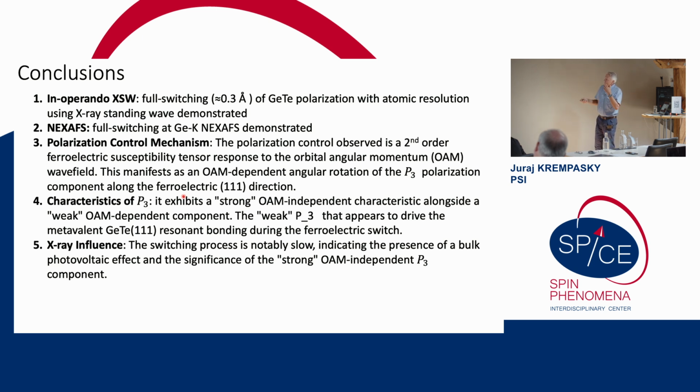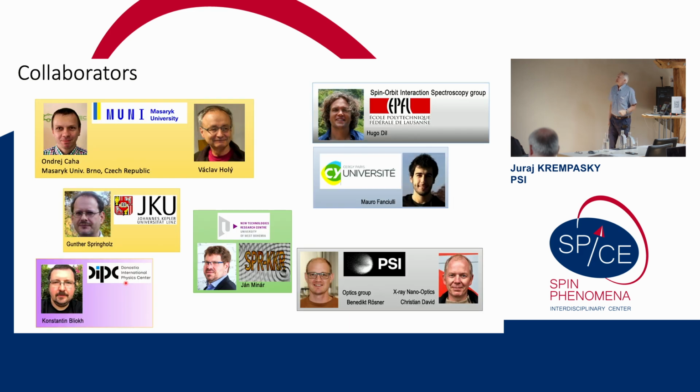At the same time, as Ritesh already pointed out, with the C3v point group symmetry there are photogalvanic effects taking place, and we simply cannot affect this bulk photovoltaic effect which is in the background. And this is something we are working on because we would like to understand whether this is how it is working under OAM. I believe it is not OAM sensitive, so the P3 is the reason why we observed